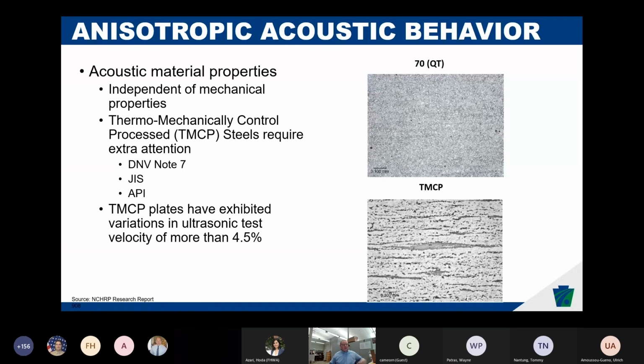And what it actually influences is the velocity, the rate at which the mechanical wave propagates through the components. So it's more significant in doing shear wave testing for weld inspections or CJP weld inspections, which was the proposal for use in lieu of radiography.